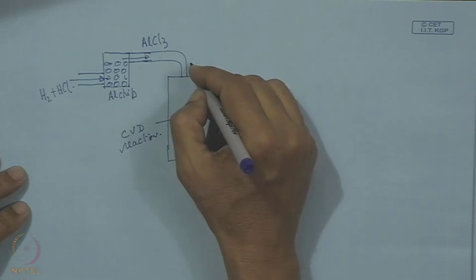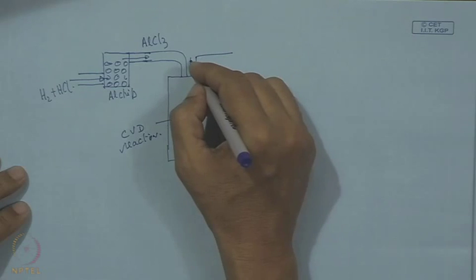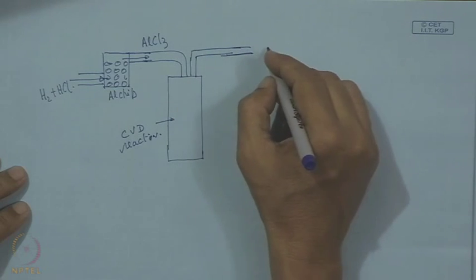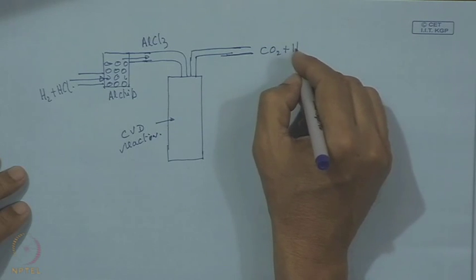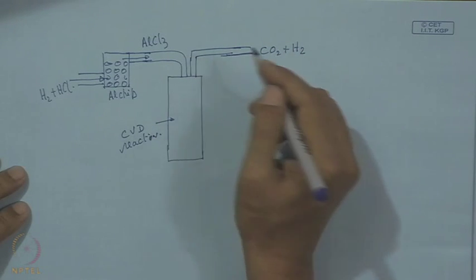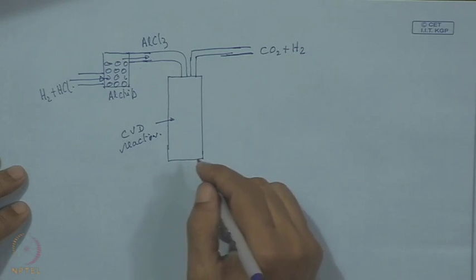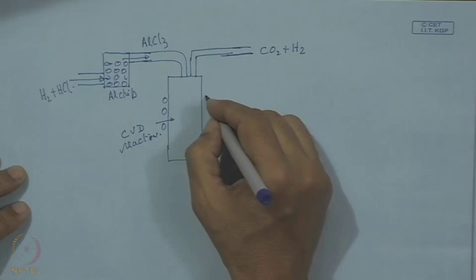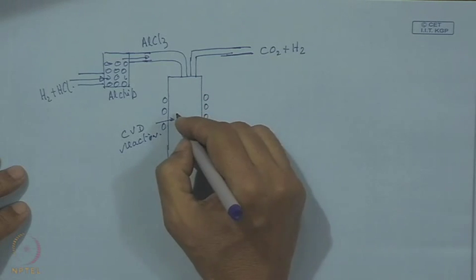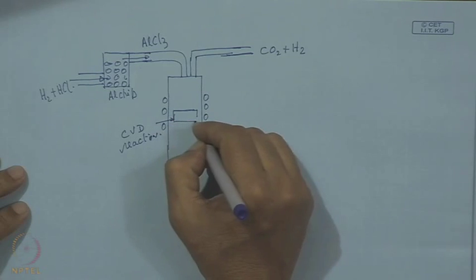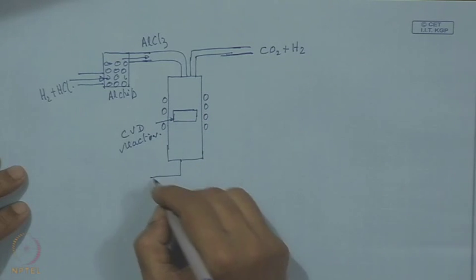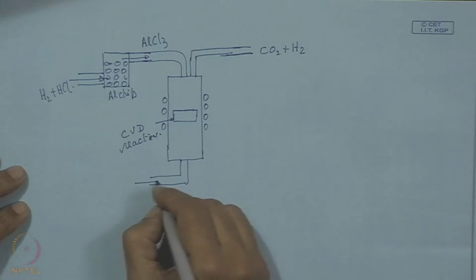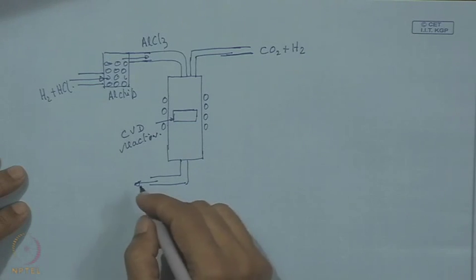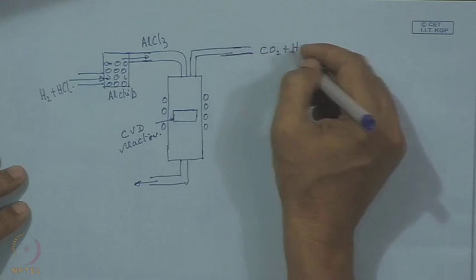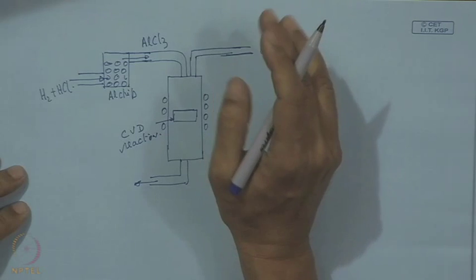Now, from this side we also have another stream which is all metered, and this is actually CO2 plus H2. So, these should be mixed in metered quantity, and we have all the provisions for getting the right temperature. We have the substrate here, and on the downstream side we must have the pumping system, which may lead to the vent. Here also we have a vent before the gases are fed into the reactor. So, all these features must be provided in the CVD system.